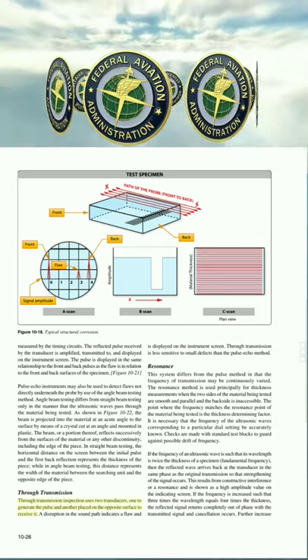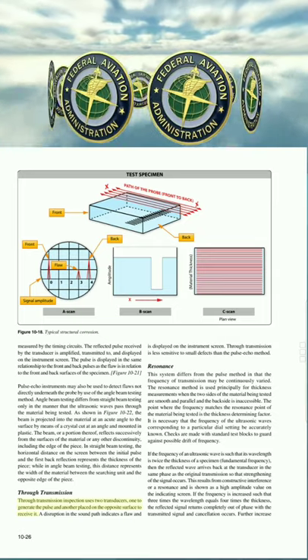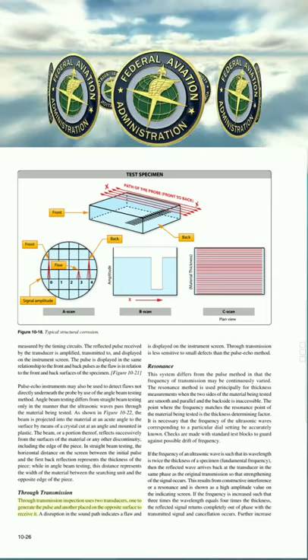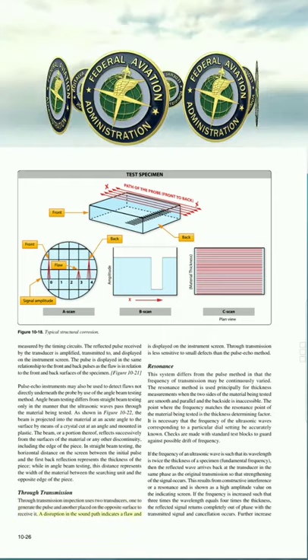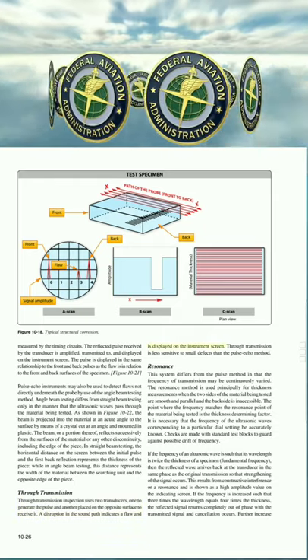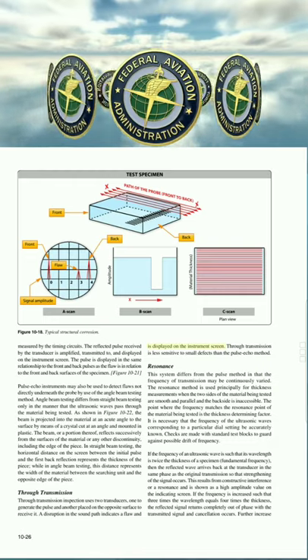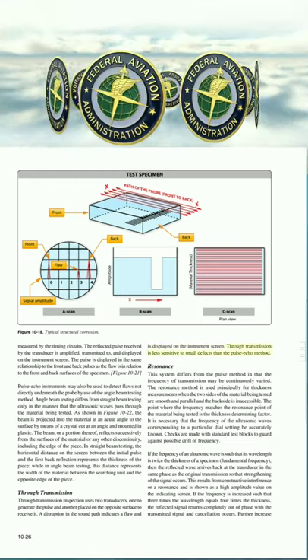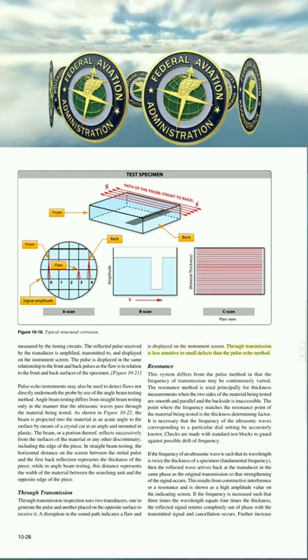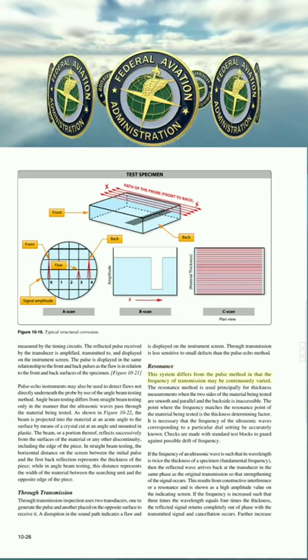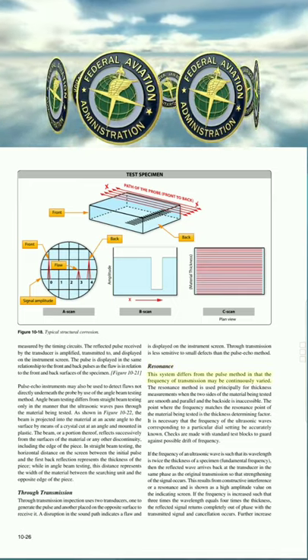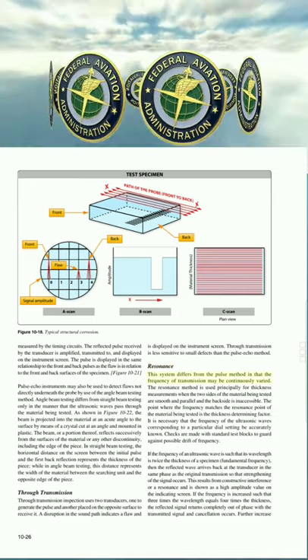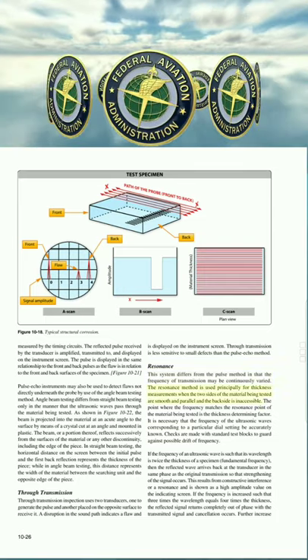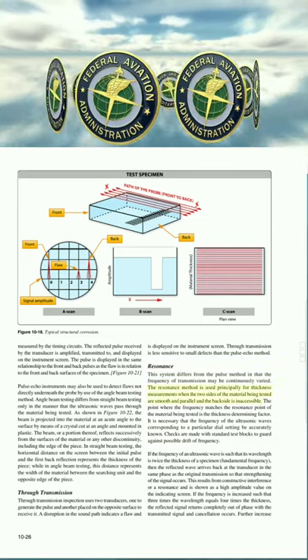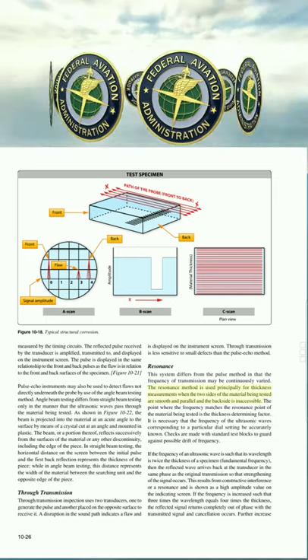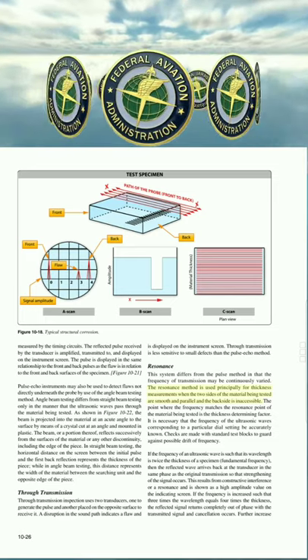Through transmission inspection uses two transducers, one to generate the pulse and another placed on the opposite surface to receive it. A disruption in the sound path indicates a flaw and is displayed on the instrument screen. Through transmission is less sensitive to small defects than the pulse echo method. Resonance. This system differs from the pulse method in that the frequency of transmission may be continuously varied. The resonance method is used principally for thickness measurements, when the two sides of the material being tested are smooth and parallel, and the backside is inaccessible.